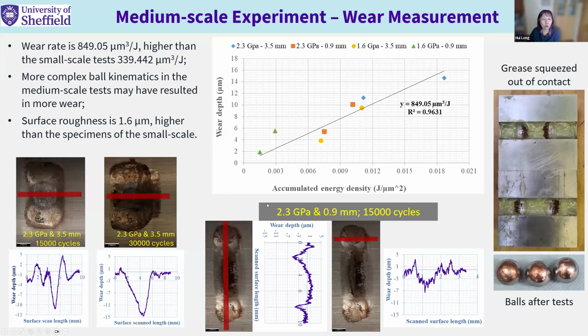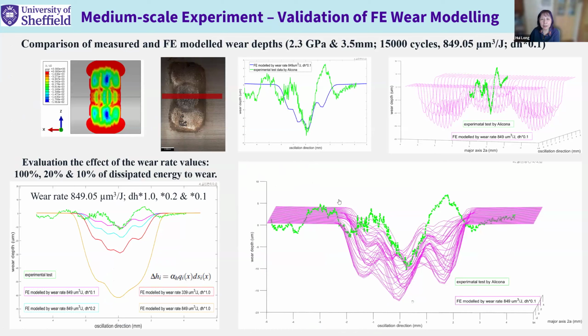Then some measurements are shown here. We measured some of the specimens, and again we can determine the wear rate from the test. As you can see, this wear rate, which as I mentioned is essential for the finite element modeling, is higher than the small test. Again, one reason is the more complex ball movement, and also the initial surface roughness of the specimens in these medium scale tests is higher than in the small tests. These measurements show some of the characteristics we saw from the real pitch bearing sections we studied. So I move on to look at finite element modeling and validation.